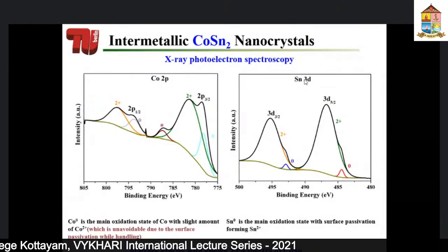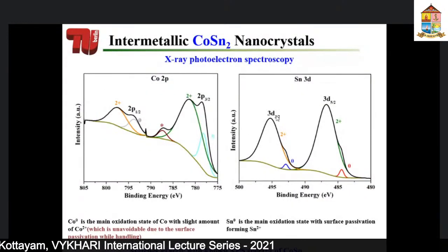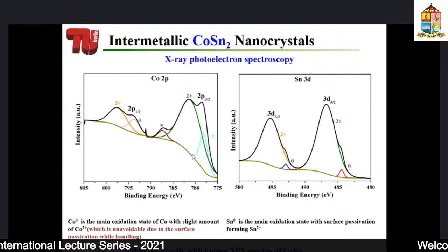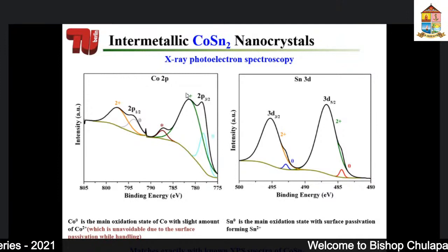Okay. I show you the X-ray photoelectron spectroscopy. This is nothing but to check the oxidation state of the material, and the peak you get around this area is relevant for the cobalt oxidation state of 0, what we produced. And then we also get something like cobalt 2+. This is because these materials are very reactive. So sometimes they react with air and form a very small surface layer. That's why your material is getting oxidized. No problem here. Similarly, we get tin 0 and a slightly oxidized phase.